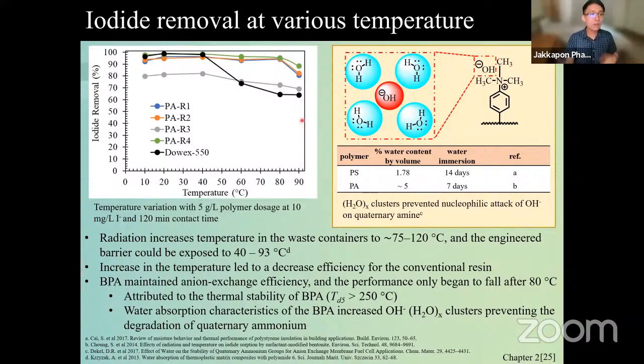But the problem with the Dowex 550 is that it only works at about 40 to 50 degrees at maximum, and then it goes down very fast. So here, I'm going to say that maybe it's because the biopolyamide has a very big molecular design. It has very long chains. As you can see in my biopolymer study just now, the molecular weight is quite high, okay?